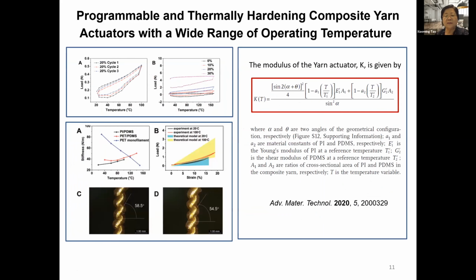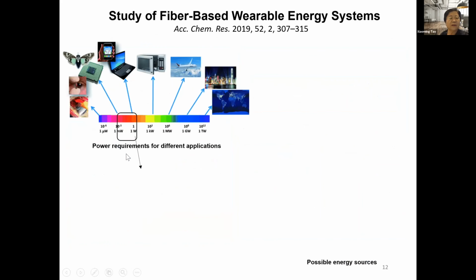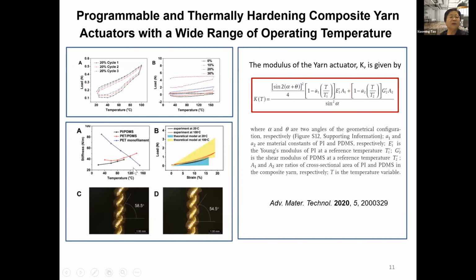Because this is an engineered composite, we actually can achieve something even more interesting. Now, this diagram here shows this very surprising behavior. It's called thermal hardening. These composites are made of two polymers, right? One is PI, polyimide. The other one is PDMS. And these individual polymers, if you heat them up, they become softened instead of hardened. But put them together, because of the structure and the internal stress, they actually behave with thermal hardening.